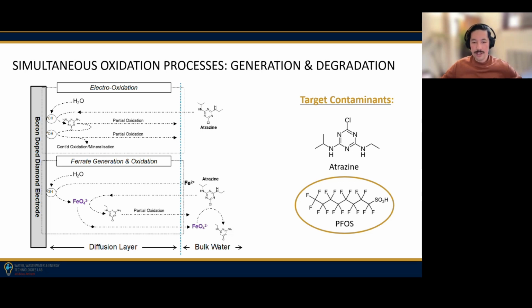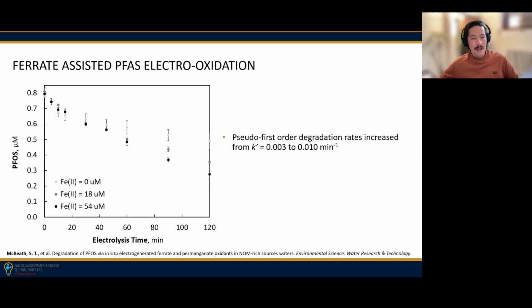So I'll show you one slide of results of that which we did with PFOS, which is one of these legacy PFAS, long-chain PFAS species. The light gray line here is the electrochemical degradation of PFOS with no iron in the water. And as small amounts of iron were present in our water, we could see that our degradation of PFOS increased. So our first order reaction rate constants increased quite a bit. And this was published in a paper. And there's another paper that talks about this ferrate formation and its usefulness in real water samples. So we're using iron levels that are typical of groundwaters and understanding how this can help increase degradation rates of common and ubiquitous micropollutants in water.